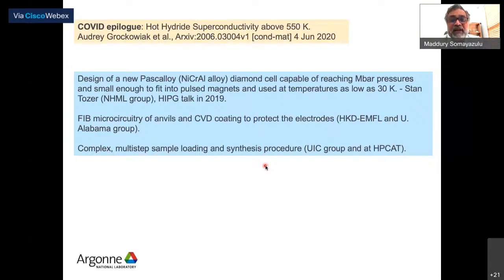The microcircuitry on the anvils was done by FIB. It's a problem. One of the pictures I showed you, where we put electrodes on the anvils, was by deposition. But when you go to very small anvils and very small samples, you need microcircuitry. That was something which was done, and it's a complex multi-step process of loading samples for this.